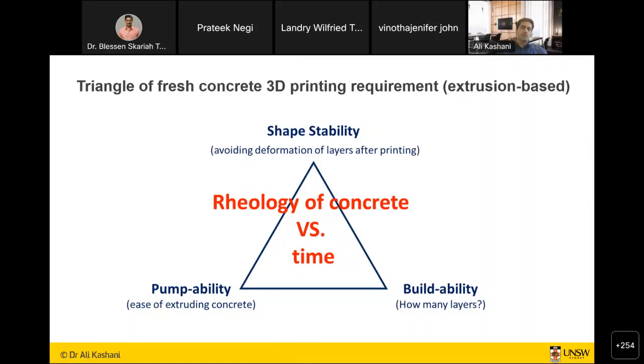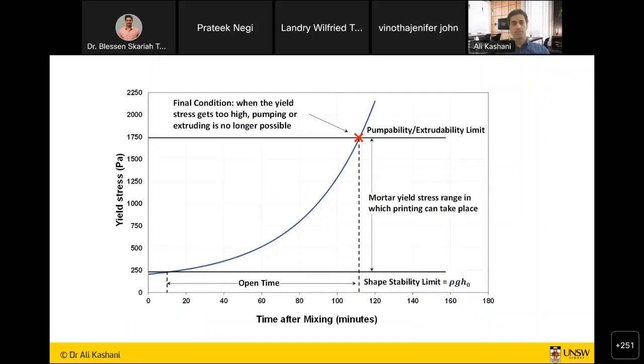So in terms of the rheology of the material, it is very important to look at three different parameters, as I said, the triangle of rheology for 3D printing. First, shape and stability, so avoiding the deformation of the layers after printing. Then pumpability, so we can pump and extrude the material, or extrudability, and also buildability. Because there is no formwork to hold the material, how many layers can we put on together before it collapses? And we use rheometers in order to assess that.